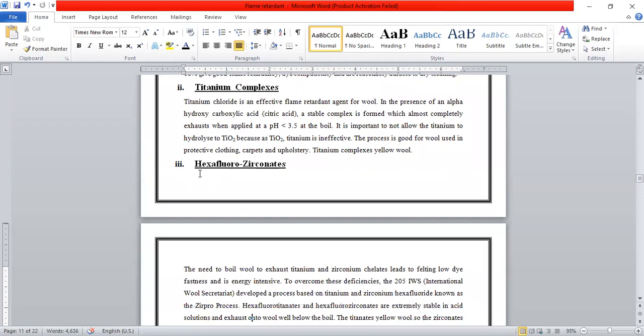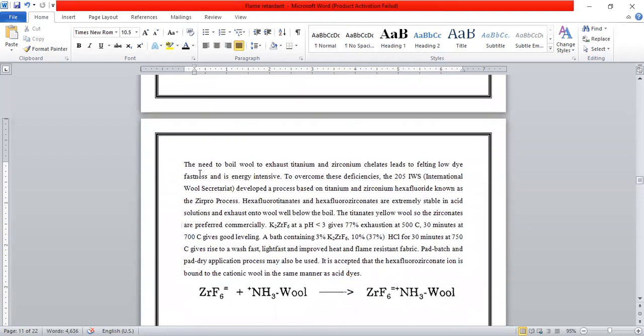And third is hexafluorozirconates. The need to boil wool to exhaust titanium and zirconium chelates leads to felting, low dye fastness, and is energy intensive. To overcome these deficiencies, the International Wool Secretariat (IWS) developed a process based on titanium and zirconium hexafluoride known as the ZIRPRO process. Hexafluorotitanates and hexafluorozirconates are extremely stable in acid solution and exhaust onto wool well below the boil. The titanates yellow wool, so the zirconates are preferred commercially.